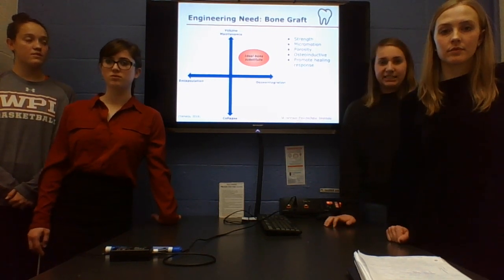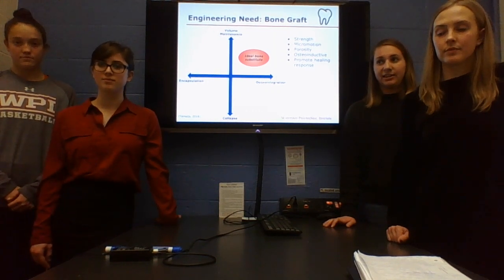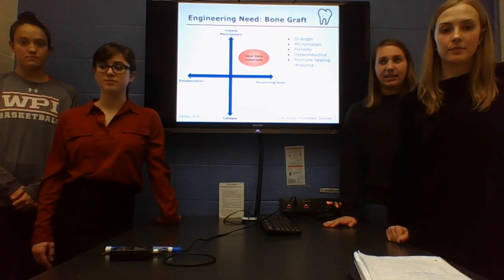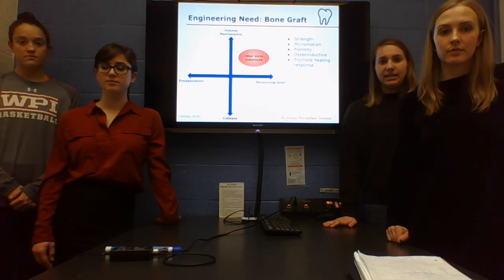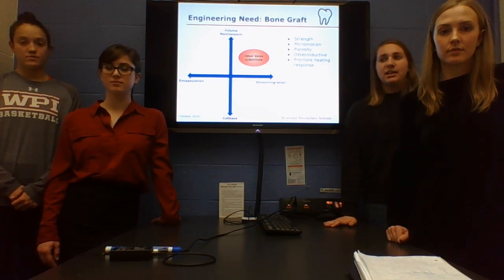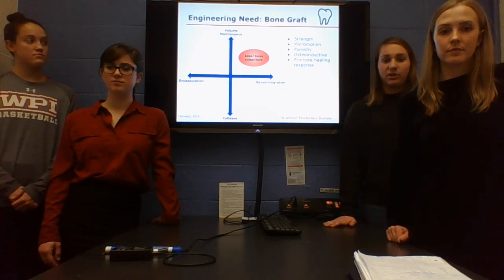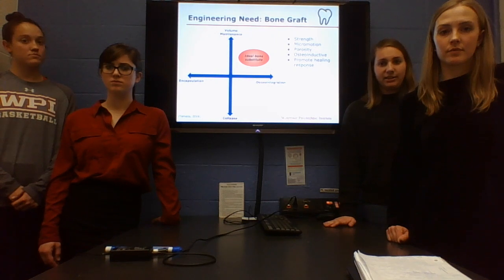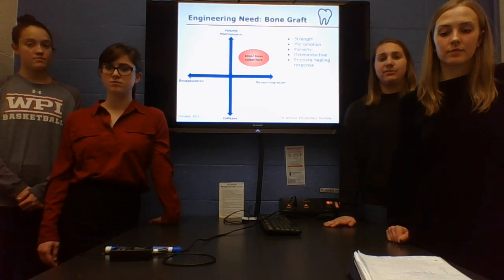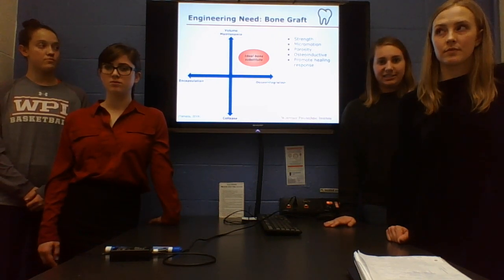Next, the porosity must be at a level that allows diffusion of the nutrients and cellular ingrowth. The ideal porosity is at a minimum 100 microns. The surface also must be osteoinductive and promote osseointegration, and the implant must not have a negative inflammatory response.